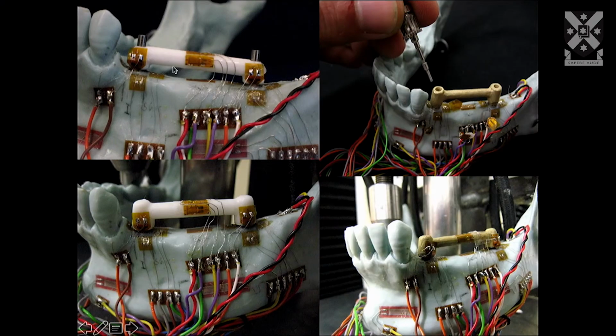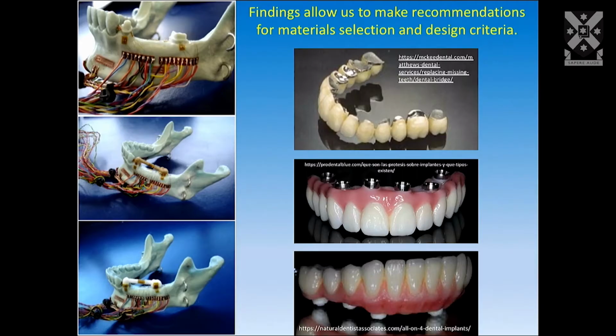So we were able to study this, as well as using very stiff materials like zirconia, which is very, very rigid, versus more ductile systems like dental alloys that you see on the right. So this combination of variables, using this in vitro approach, enabled us to look at, do we cement retain, do we screw retain? Do we use metallic systems like you see here, or ceramic systems like you see here? And that enabled us to then inform that type of treatment planning.